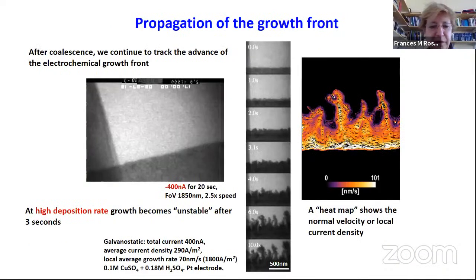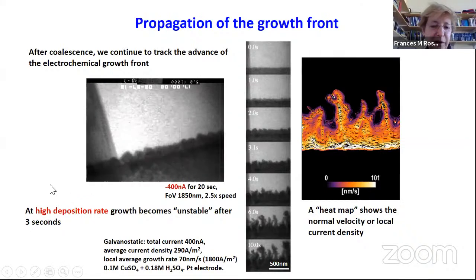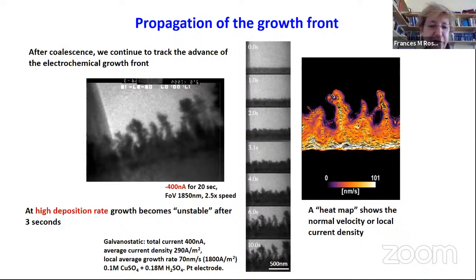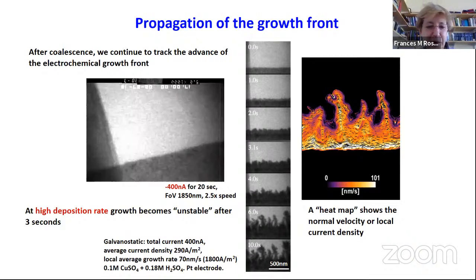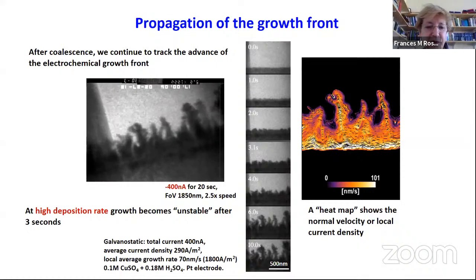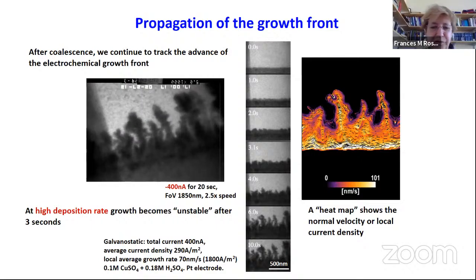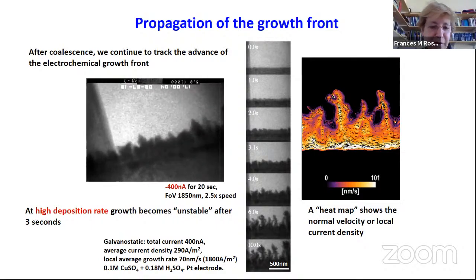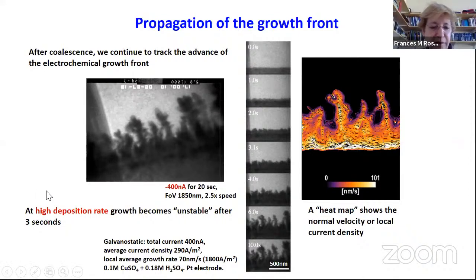All right, here's another example. We've grown copper on the electrode, and now we're going to grow so much copper that it starts growing sideways off the electrode, and we can see how the growth proceeds as a function of time. Again, a very short video, I did speed it up a little bit, but what you can see in the video is that the growth starts relatively flat, and then it becomes rougher and rougher until we get these dendrites formed after a few seconds. And so the high deposition rate leads to a growth instability.